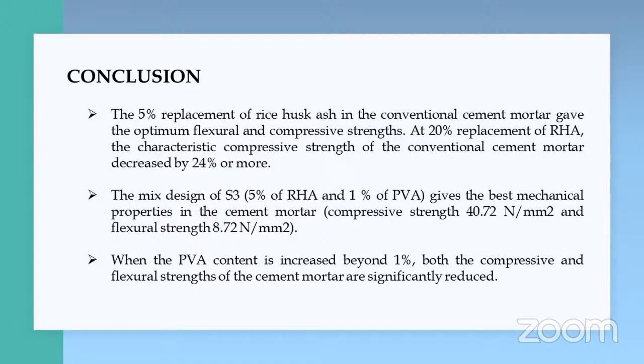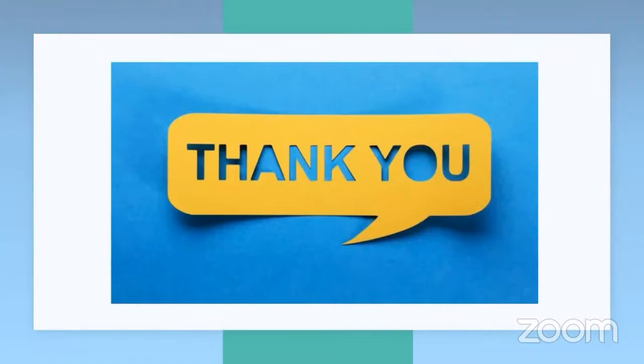The mix design of S3, with 5% RHA and 1% PVA, gives the best mechanical properties in the cement mortar: compressive strength of 40.72 Newton per square millimeter and flexural strength of 8.72 Newton per square millimeter. When the PVA content is increased beyond 1%, both the compressive and flexural strength of the cement mortar are significantly reduced. Thank you.